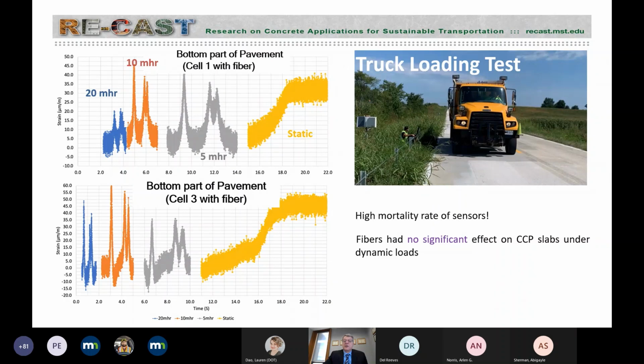This is a very, very dry consistency with the paver going over it, and then the consolidation that followed. So we had a low survival rate, and we were able to pick up the signals with only very few sensors. But from the testing, what we learned is that the fiber really had no significant effect on the dynamic loading, with and without fiber. So this is without fiber versus with fibers. Did not seem to have any positive effect.